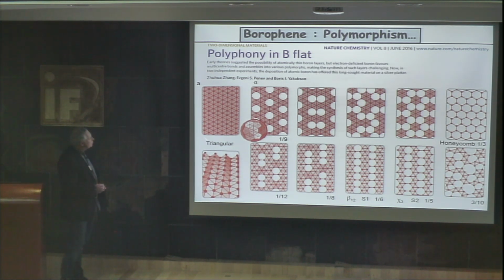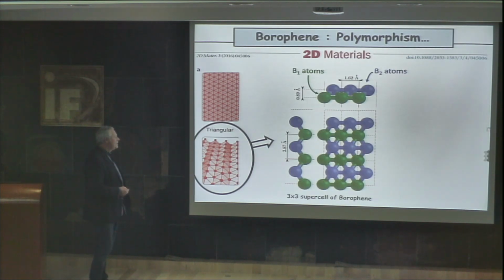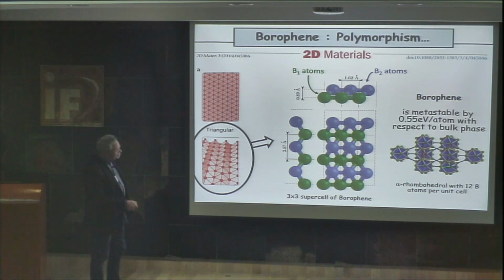So you can start from the triangular lattice that I showed you with this buckling, and if you extract boron atoms, you can go to different situations until you reach this honeycomb system, when you have only one atom of boron on the hexagonal lattice. And from theoretical calculations, there are really three phases that are more stable than the others. One is the triangular here, you have this beta 12 and you have this chi 3 here, that are the most stable compared to the bulk system. In fact, the bulk system for boron is this one.